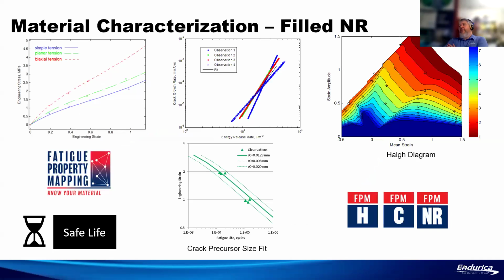And now here the materials characterization gets a little bit more sophisticated. So we're going to do the hyperelastic, the core, and now we need to characterize the mean strain effects, right? With the non-relaxing module. So the materials characterization is going to look something like this. We're going to have stress strain curves just like we had before. We're going to have a crack growth rate curve, which we did not before. All we needed was the fatigue limit. Now we need the full crack growth rate curve. And we also need the strain life curve so that we can use these two results to calibrate the crack precursor size, which for this example turns out to be 12 microns. Once we've defined all these, we can also run the non-relaxing experiments.